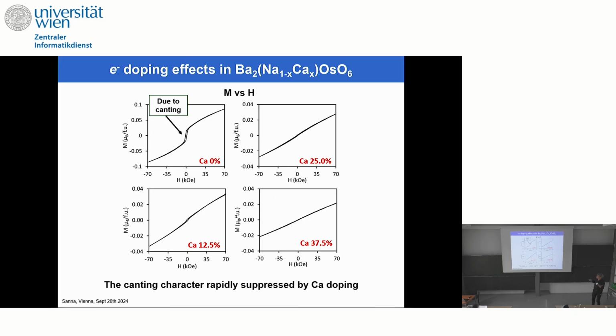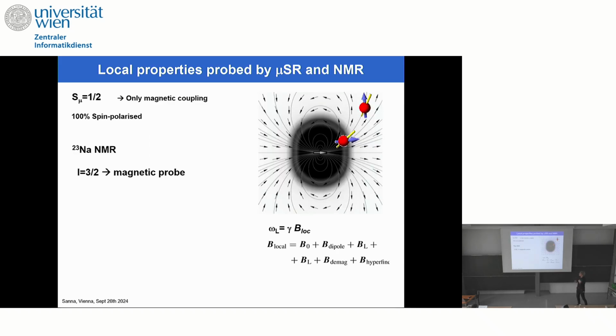And what is found is that the canting is suppressed almost immediately. You can see from magnetization measurements that here we have a kind of S shape, which is due to the canting, while it is almost negligible here for 12.5%, and then we completely lose the ferromagnetic-like character, and we only have a paramagnetic character. Okay, now, what about the local probes?